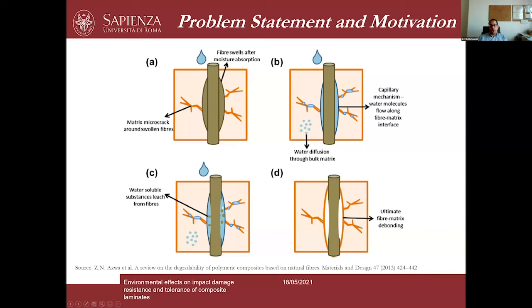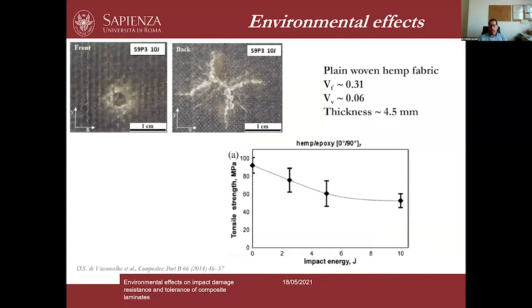And when this water actually reaches the fiber matrix interface, what happens is that the fiber is pretty rich with constituents which can be easily solubilized by water. And so we have a significant degradation of the fiber, and at the same time, a significant degradation of the fiber matrix interface, which actually leads to ultimate fiber matrix debonding. So it is expected that the mechanical properties will be significantly affected by the presence of water.